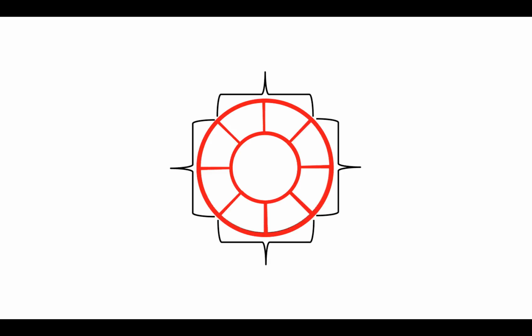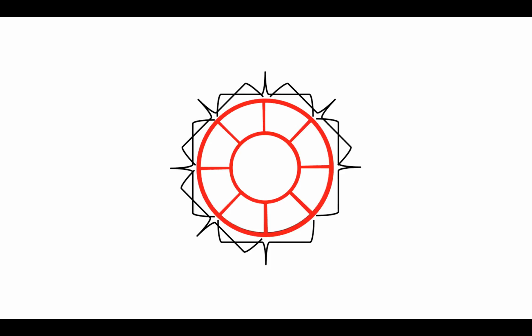So in getting ready to put on my second layer of prepreg arcs, instead of putting the second pieces right on top of the first ones, I will stagger them so that they overlap. So here I have two layers of arc-shaped prepreg. Like this. That's the first one, second, third, fourth. Then I start overlapping: 5, 6, 7, 8. I would accomplish the same thing if I put the arcs on in this order, which is what I'm going to show you next. 1, 2, 3, 4, 5, 6, 7, 8.